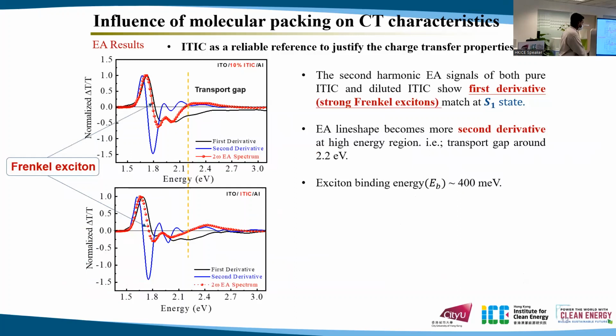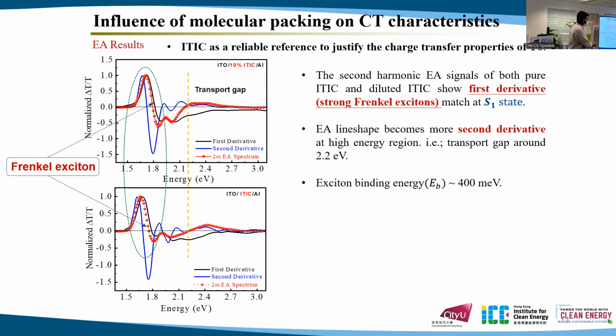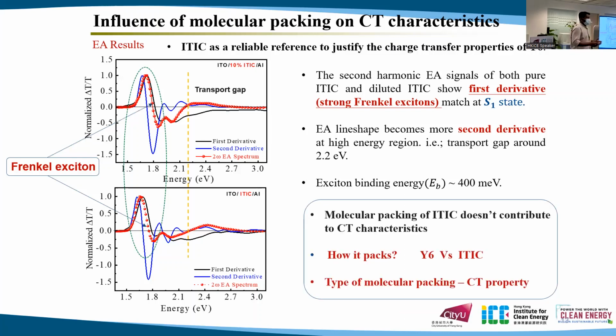In both cases, even though we increase the concentration of ITIC in the polymer matrix, still in the S1 state, it is more Frenkel excitons. We also observe the same transport band gap and exciton binding energy from a similar approach. So what is happening here is that not just molecular packing, but how it packs is important.